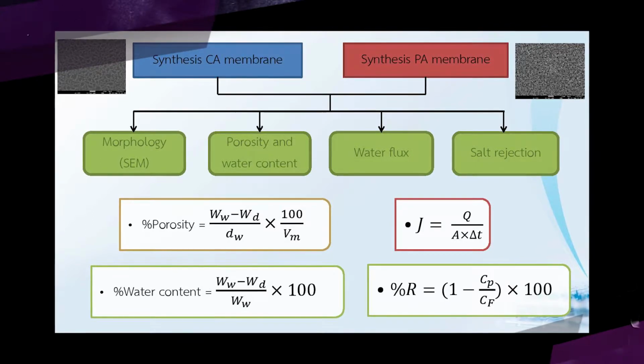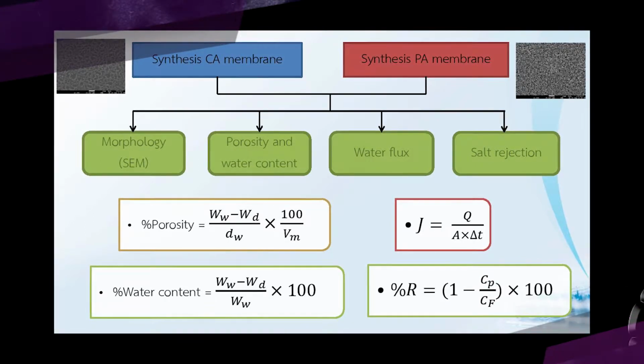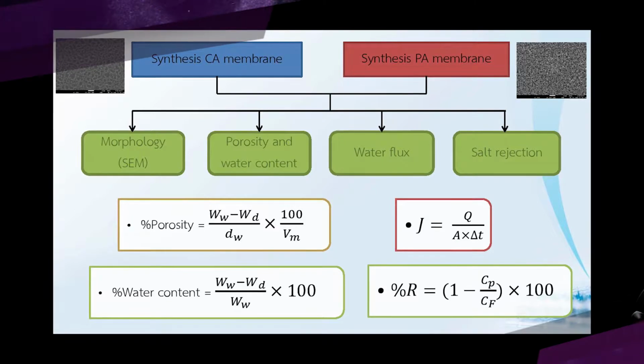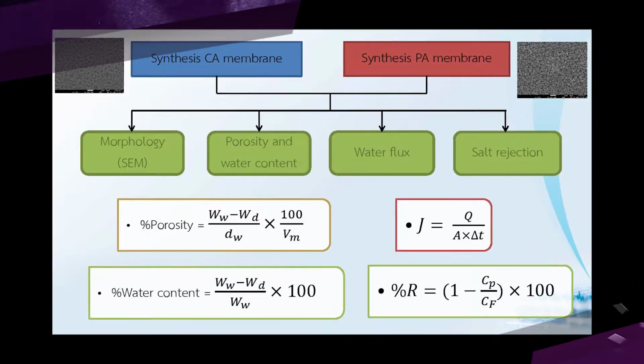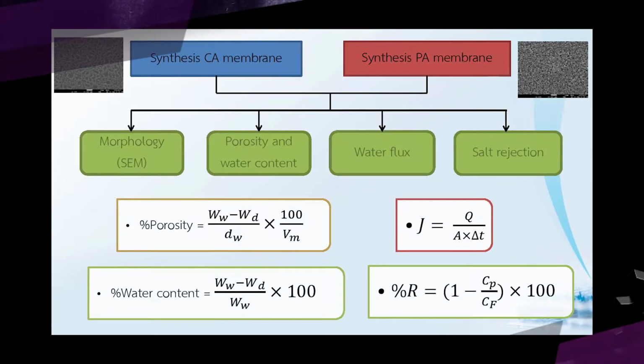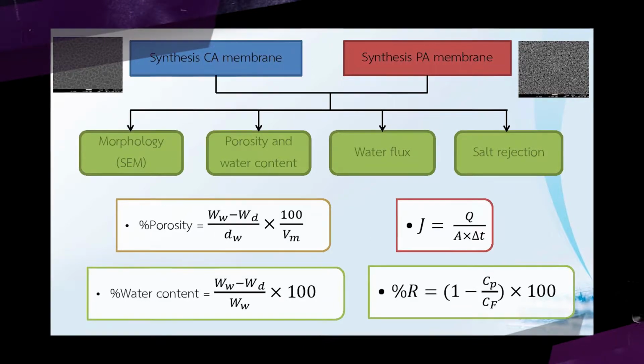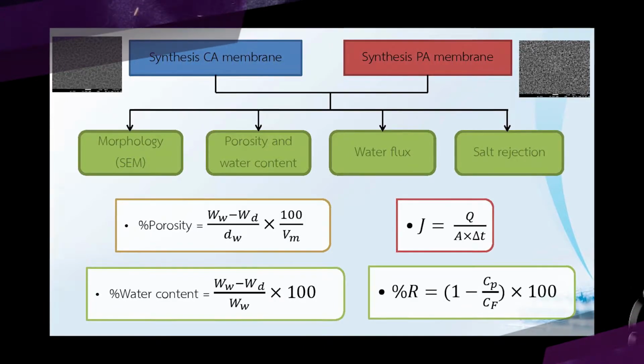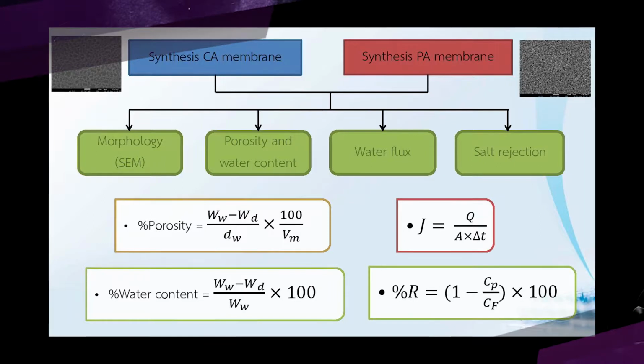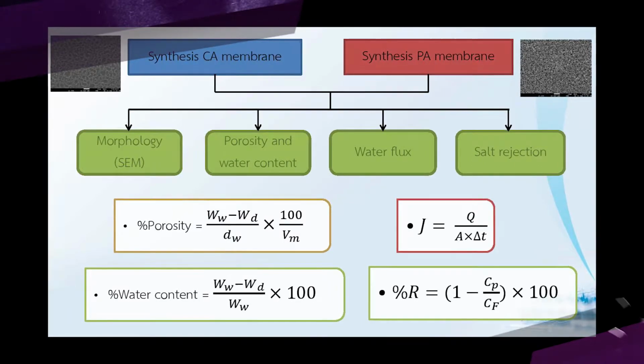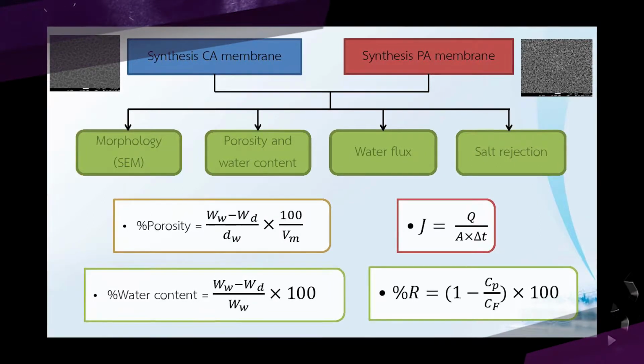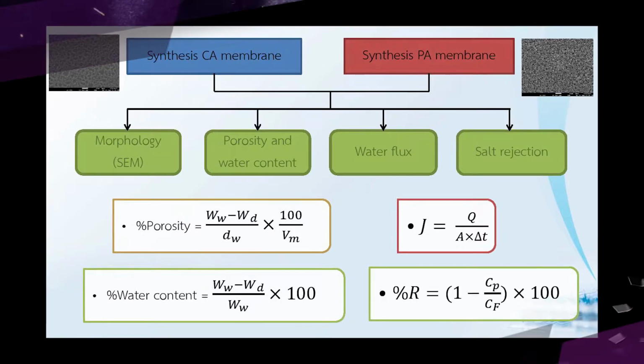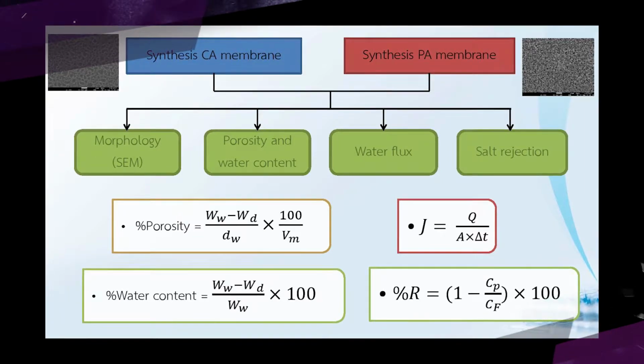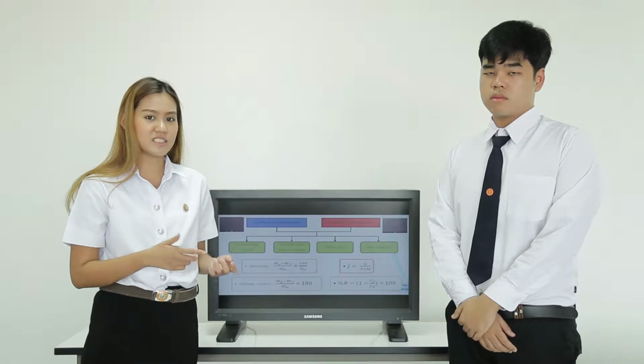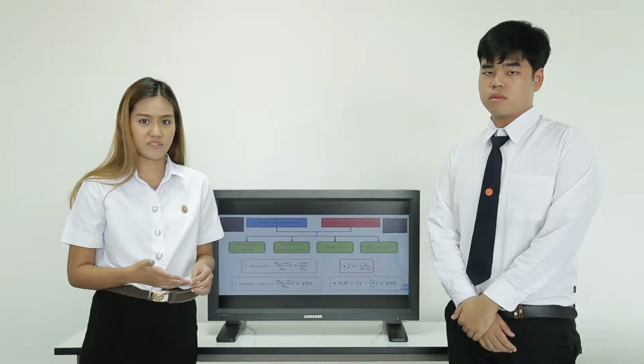Finally, we will compare which one is better between cellulose acetate and polyamide membrane. And we found that when we add more polyethylene glycol, the characteristics are better, and the water flux and salt rejection will increase.